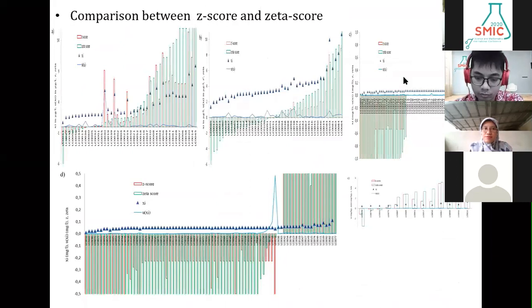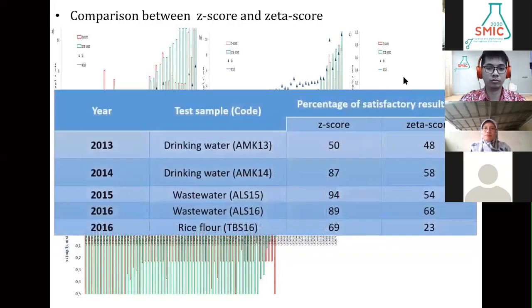To assess how realistic the participants' uncertainties are, in this study, the data scores of the PT results were evaluated, and as a result, as you can see in the graph, over and underestimated uncertainties reported by some laboratories in comparison with the correlated standard deviation for proficiency assessment had clearly affected the data score. For our observation, although the participants achieved satisfactory results on the basis of the data score, the over and underestimated uncertainties caused a large deviation between the Z and the zeta scores that yield difference in percentage of satisfactory results, as shown in this table.